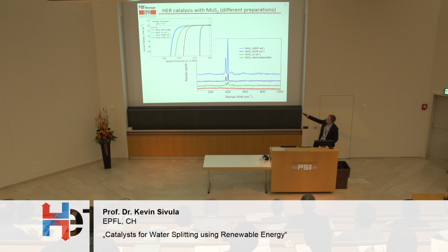And if we look at the performance again, here's the same graph that I showed you before, we can see that this correlates very well with the activity. In fact, a higher crystalline material performs poorer in this case. And this aspect for these materials is well known, but before we never had a way to really vary quite systematically the amount of defects, for example, in the material. So in our ongoing studies, we hope to elucidate exactly what the defects are in these cases that are catalytically active for this water reduction reaction and enable us to exploit them a little bit more.